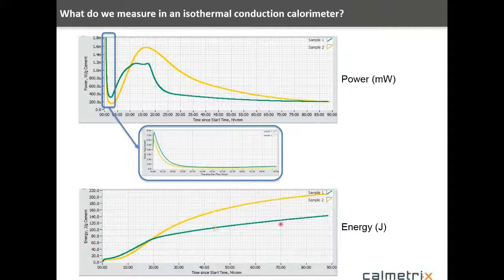And you see smoothly increasing curves here. That's because these are continuous integrals of these curves. So if you go to 10 hours, here it's basically taking this curve 10 hours and integrating under this slice of the curve and generating that as a data point at 10 hours.